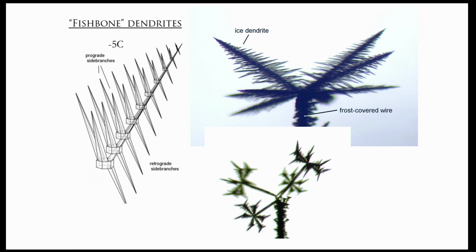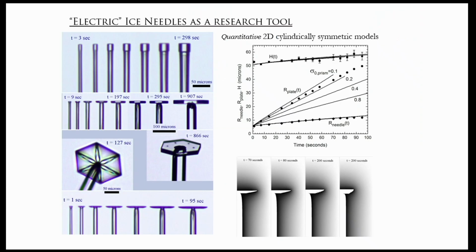The structures were nice because we saw this a lot, and we really had a hard time figuring out what that was until we started doing it on C-axis needles. And here's one where we made a C-axis needle, and then some dendrites, and then moved back to needles. And now you can see where the axes were if you roll it around a little. And so we made this model, and that fits pretty well. And you can do quantitative measurements. It's a real research tool now.